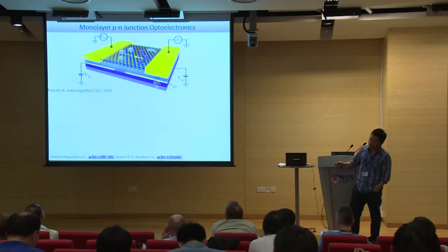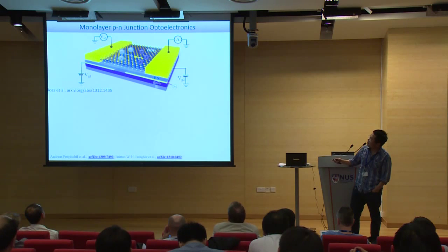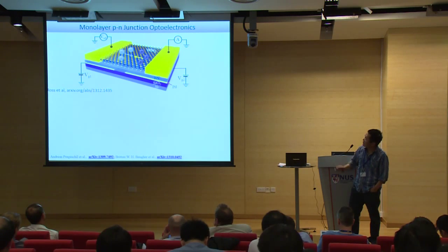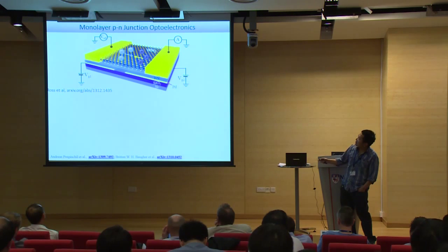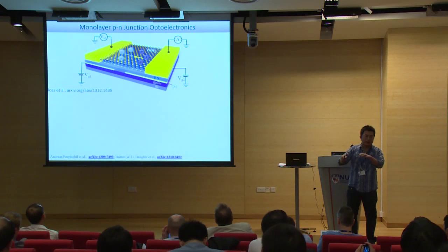We use boron nitride as a dielectric layer, and underneath the boron nitride, we create two metallic bottom gates, so we can then transfer a monolayer tungsten selenide on top. In this case, these two split bottom gates can control the carrier densities above them, so we can create the PN junctions.